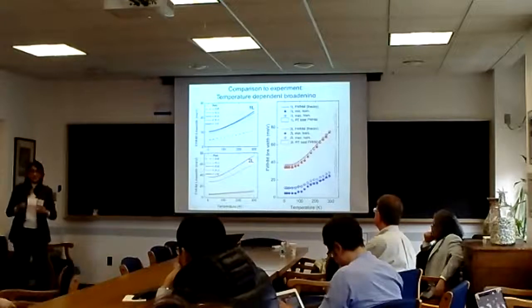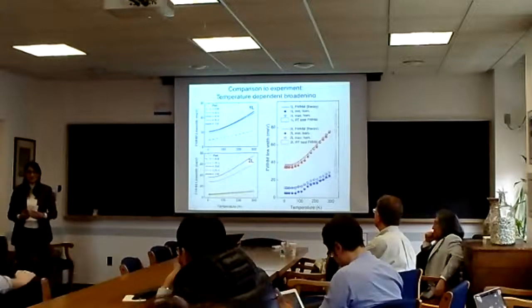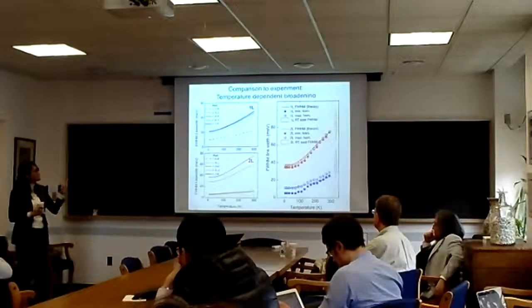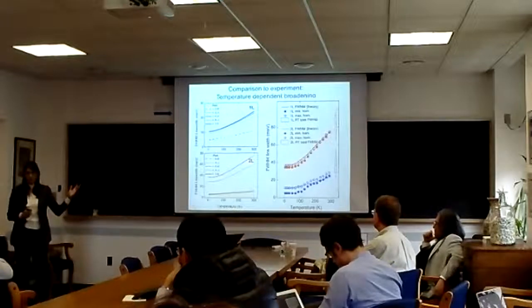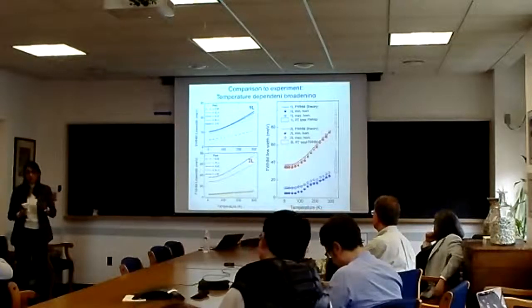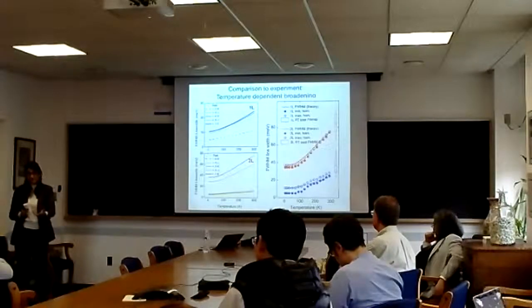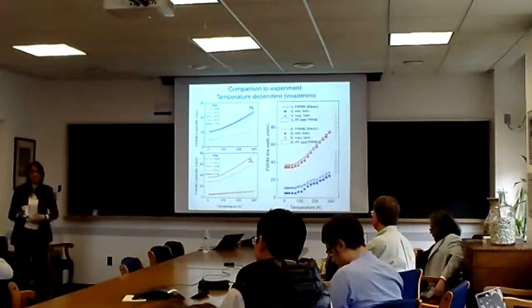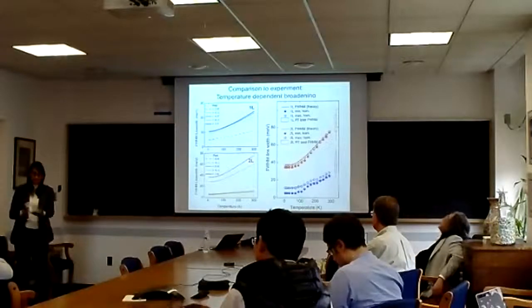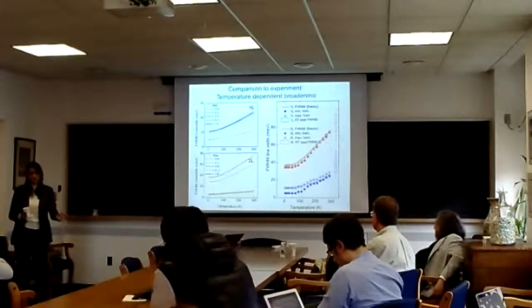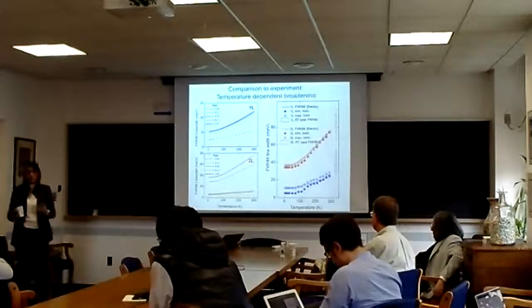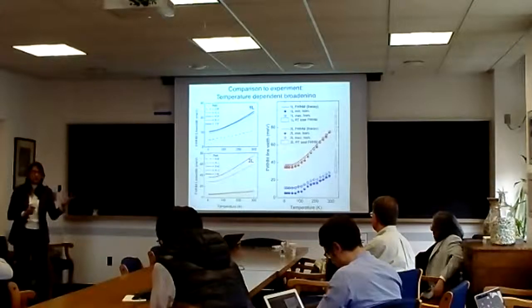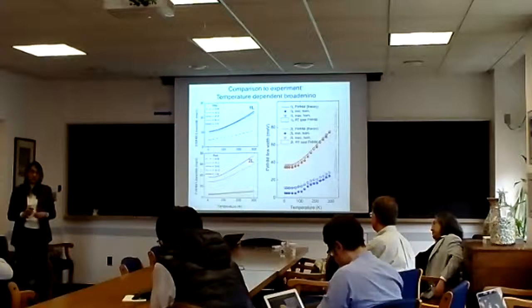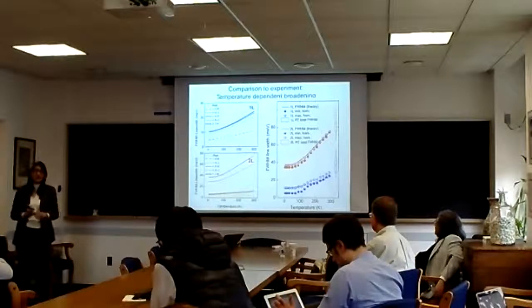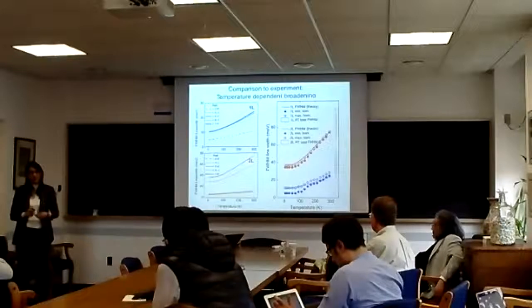In the sense that it definitely exists, it's just that I didn't necessarily probe it or use it, because in this linear optics regime that I'm working with, I'm not going to probe that directly. There are some effects of it. For example, the photoluminescence yield, if you measure these materials, will change because of this spin-orbit splitting. So tungsten would be different from molybdenum, but those were not the physical processes I was concerned with here. So in MoS2 there is no dark state, but in tungsten there is. That will affect different types of properties compared to what I was discussing.